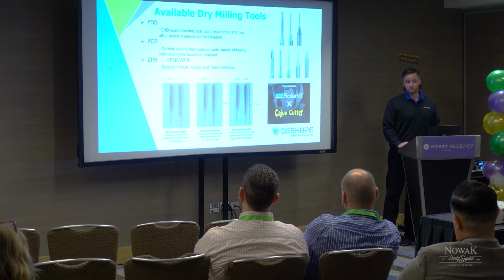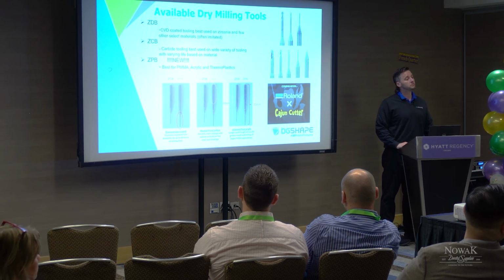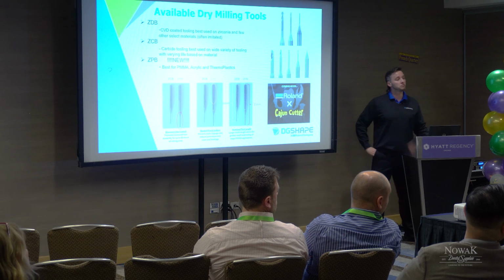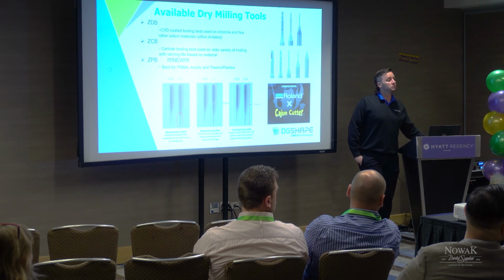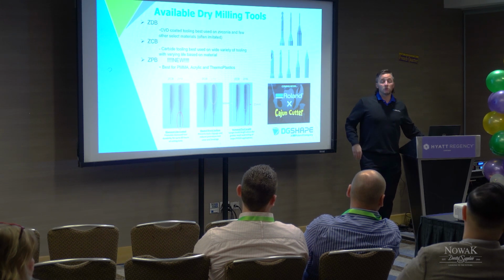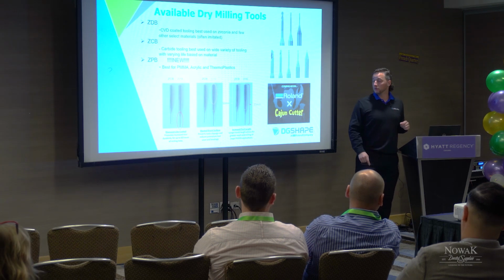Any questions? There's been times where I've had to use a 30 millimeter puck of zirconia, and it'd be great to have a longer length tool. All right, good. That's actually a really good thing to bring up. ZPB is capable of milling zirconia. It is cheaper than a diamond coated tool for zirconia. Those tools are not going to last as long on zirconia. That coating is not enough to protect it against the zirconia. It's better for plastics and acrylics.